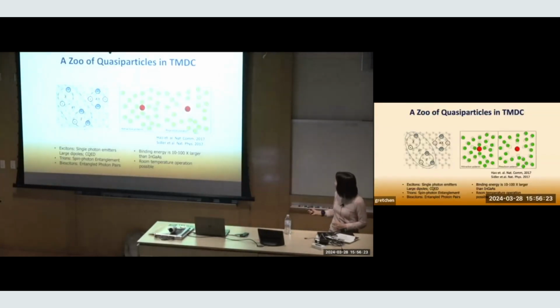Okay, so in these materials, we have a zoo of quasi-particles. What I mean by quasi-particles is, basically, either a bound electron hole pair, that's an exciton. I showed you the excitation of an electron from the valence band to the conduction band. What you actually left behind is a hole. The hole is positively charged, and there's a Coulomb attraction between the two that gives you this bound state called an exciton. And the binding energy is surprisingly large. In gallium arsenide, you have excitons, but nobody really cares about them at room temperature in devices because the binding energy there is about 5 to 6 meV. And thermal energy, kBT, is about 25 meV at room temperature. So the exciton is not stable at room temperature in gallium arsenide devices.